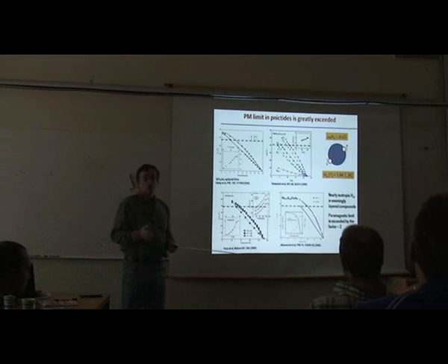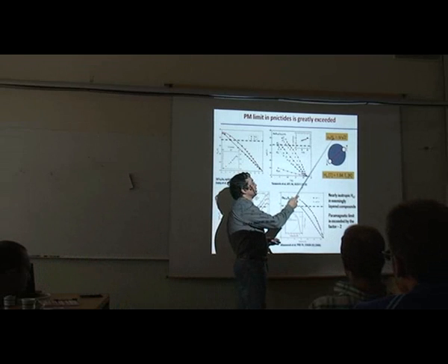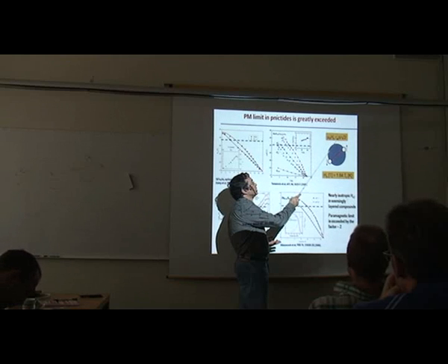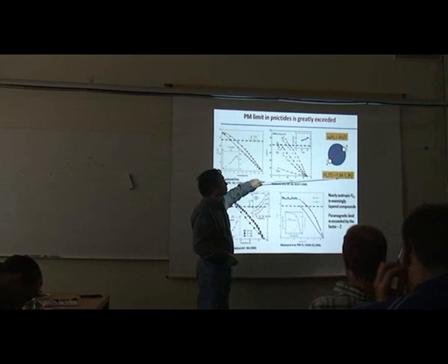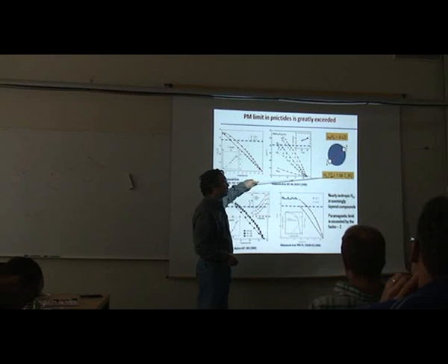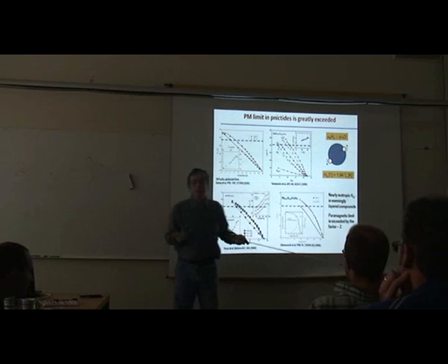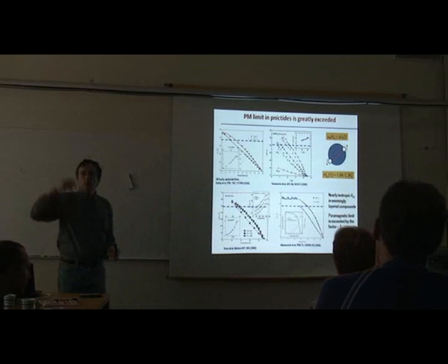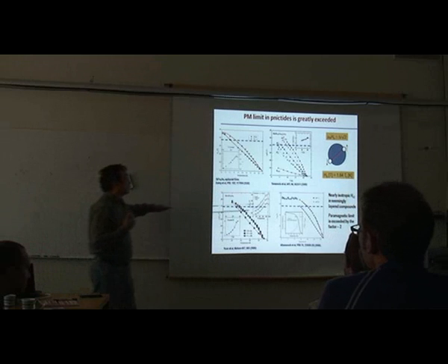However, all of them are well above the BCS paramagnetic limit. Again, that's how the paramagnetic limit in the BCS theory is calculated: Zeeman energy equals the superconducting gap divided by square root of 2. So the same formula expressed in terms of Teslas and Kelvins looks like this. HP in Tesla is 1.84 times Tc in Kelvin. So if Tc is 20 Kelvin, then the paramagnetic limit will be smaller than 40 Tesla. And they can go up to 60 and 70 Tesla and still see superconductivity, like in all these cases.